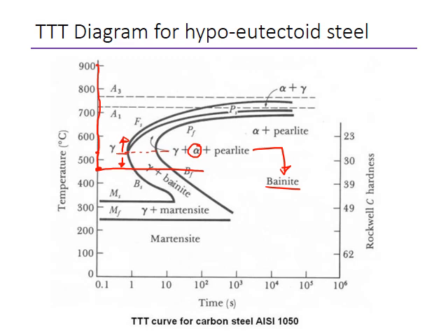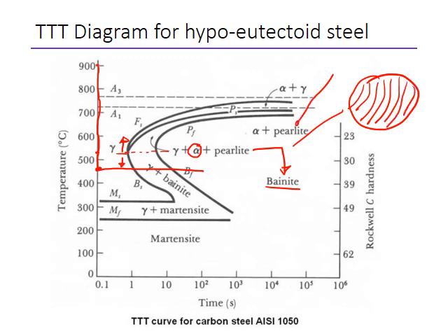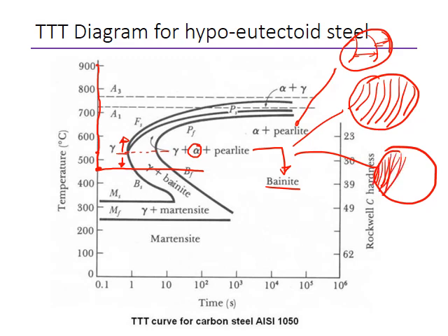Some people say that bainite is really pearlite, but so fine that you can no longer recognize the lamellar microstructure typical of the eutectoid steels. So remember that pearlite was kind of a lamellar structure. So the lower the undercooling value, the higher the distance between lamellar plates; the higher the undercooling value, the finer the pearlite form.